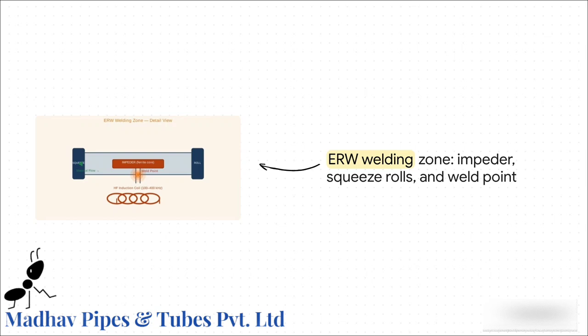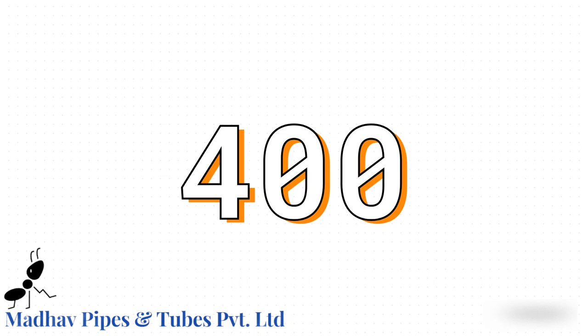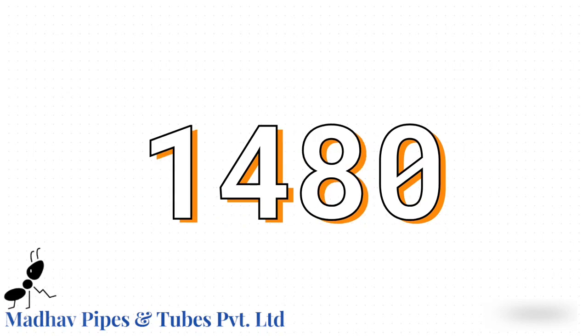This concentrates all the energy exactly where the weld point is. So the key here is the sheer amount of energy being directed by that impeder. The tube passes through an induction coil operating at a mind-boggling frequency, rapidly alternating between 100 and 400 kilohertz. That is incredibly fast. And because of that intense 400 kilohertz frequency being forced right along those thin steel edges, an enormous amount of heat is generated purely through electrical resistance. We are talking temperatures up to 1480 degrees Celsius.